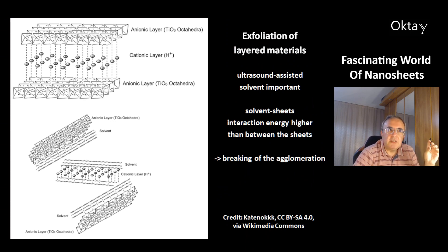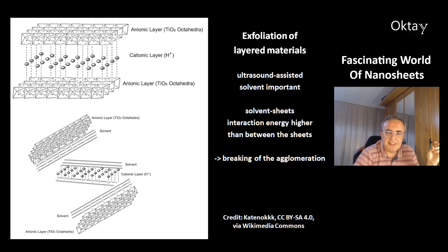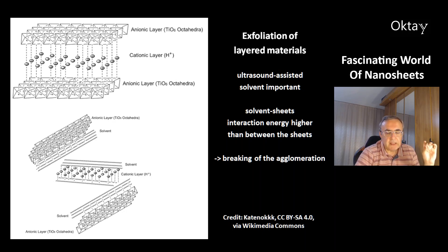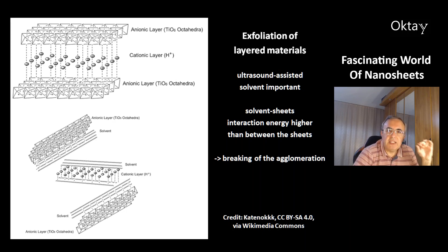This is how the exfoliation of layered materials works. You need ultrasound assistance, and the solvent is very important. The solvent-sheets interaction energy needs to be higher than the energy between the sheets — then you can break the agglomeration and obtain the nanosheets.